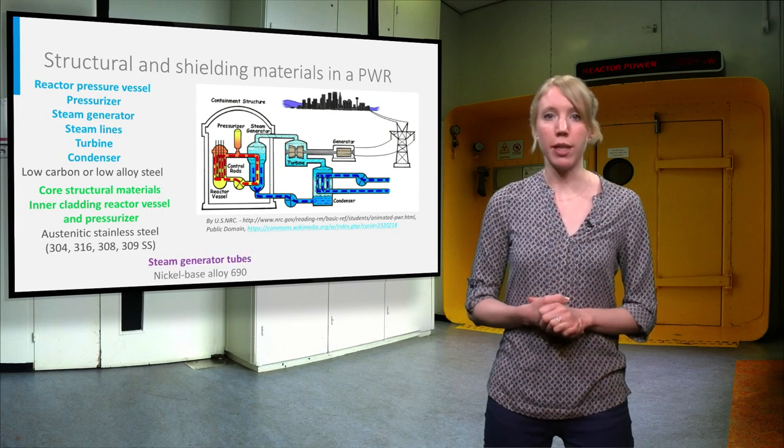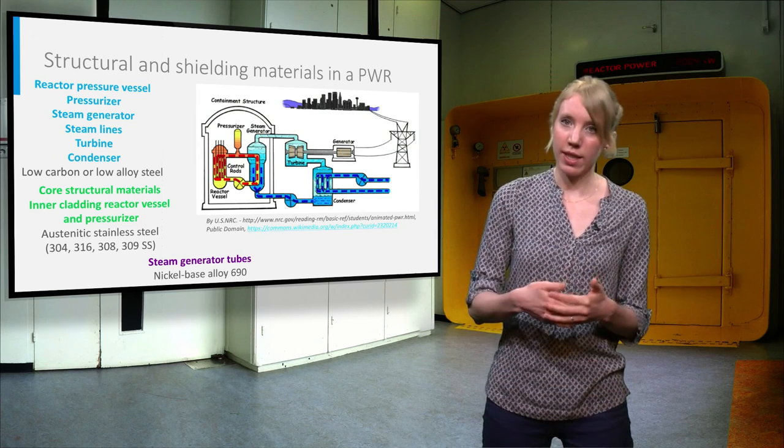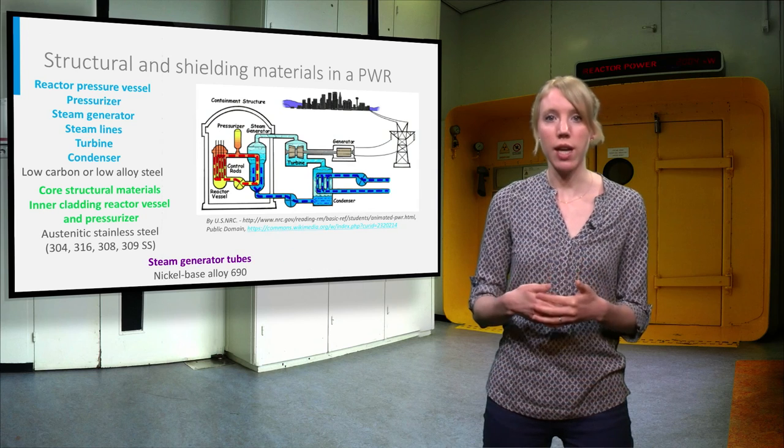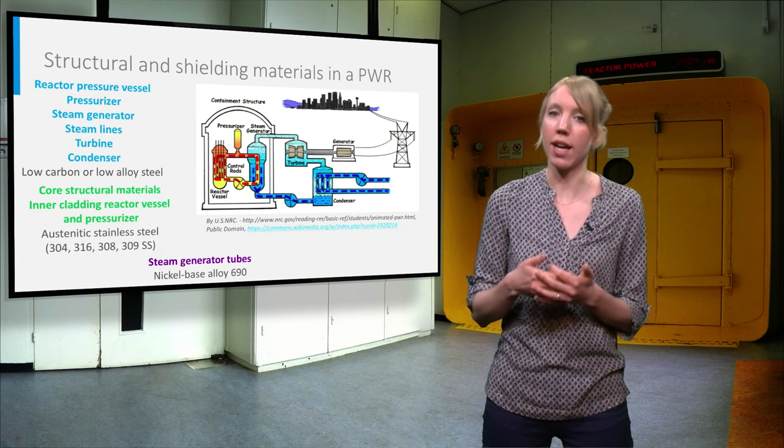The steam generator tubes are made of a nickel-based alloy. Austenitic stainless steel and nickel-based alloys have been selected because they have low corrosion rates at high temperatures.